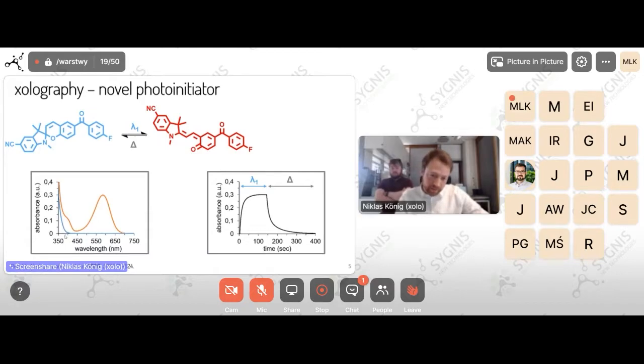And when it absorbs light in this region, then it opens to this merocyanine form, the red form here on the upper right side on this page. And this open form now has a very large conjugated pi system, and that results in absorption in the visible. And this you can see here in the absorption spectrum by this pronounced visible band of this orange line here. So spiropyrans can be switched with a wavelength lambda 1 in the UV region to a merocyanine, but this merocyanine relaxes back thermally, and it does that quite quickly if you want.